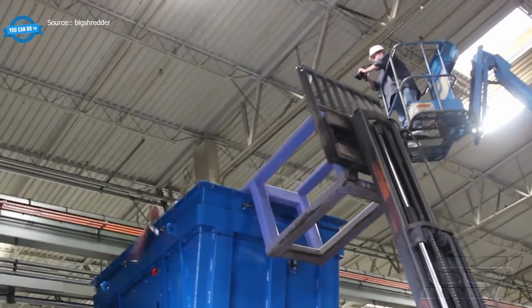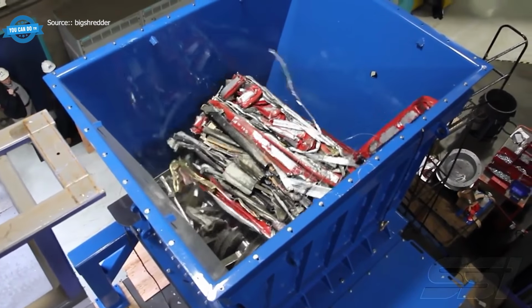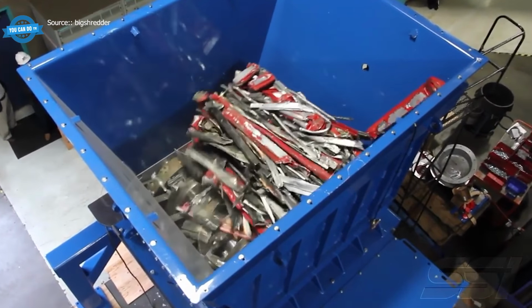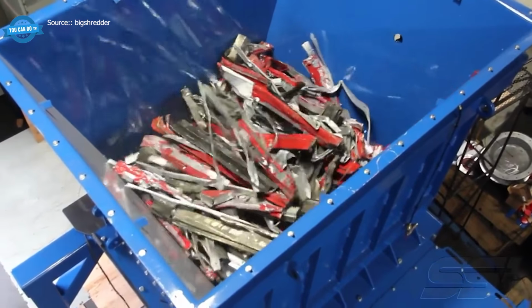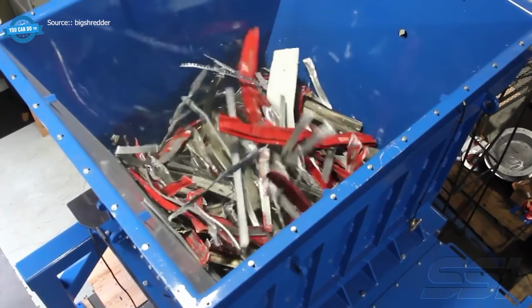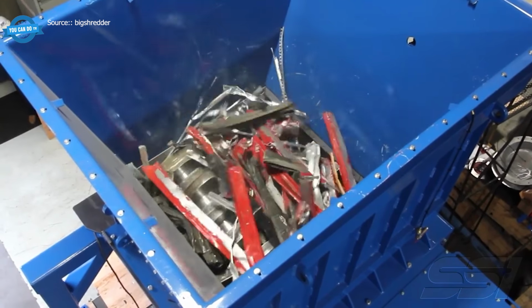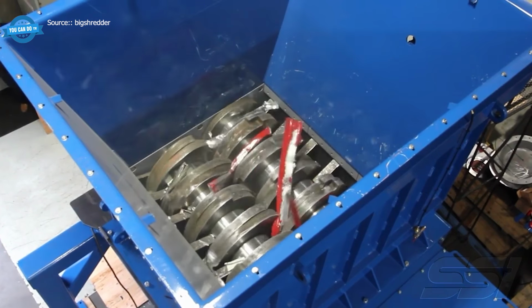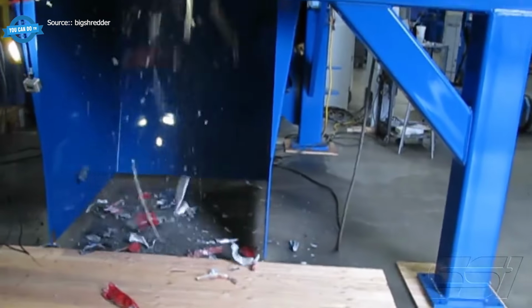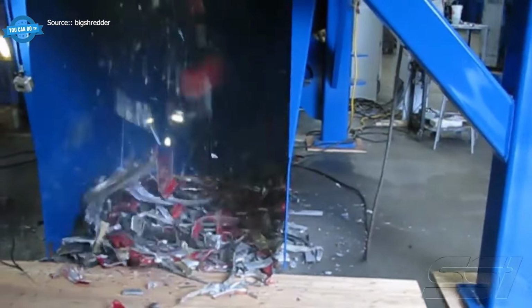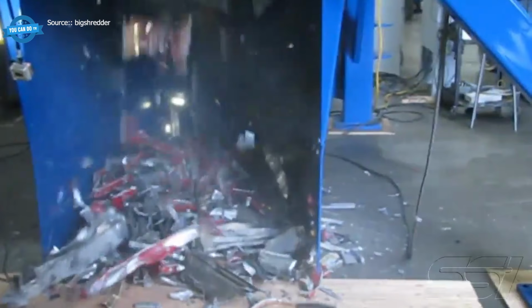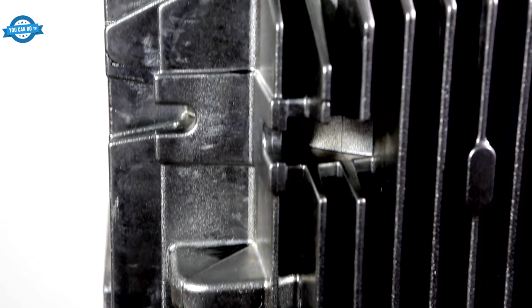Every foundry running aluminum blends fresh primary metal with recycled scrap in careful ratios because the chemistry has to end up in a narrow specification window. Bad scrap will slip into a good melt without warning, and the whole batch of castings comes out porous. Nobody wants that conversation with the customer.